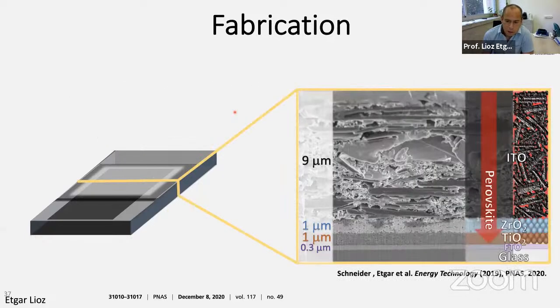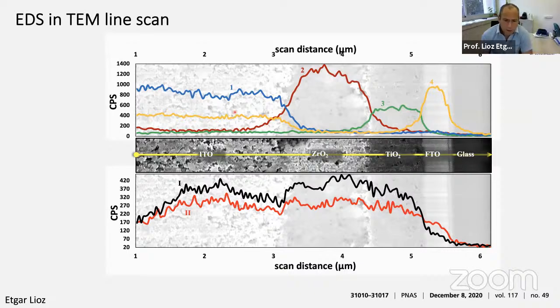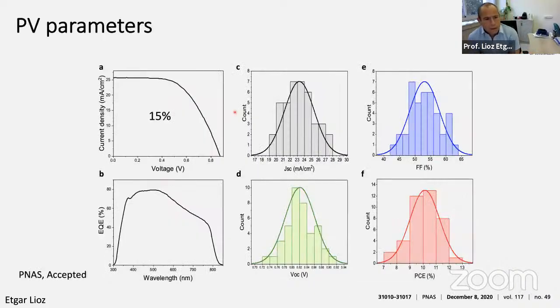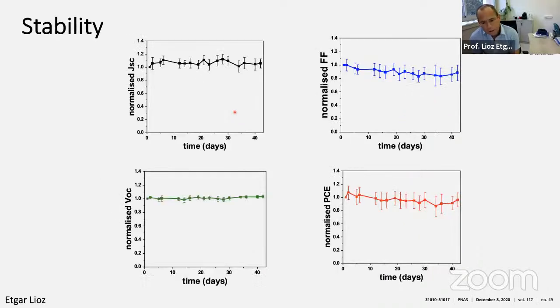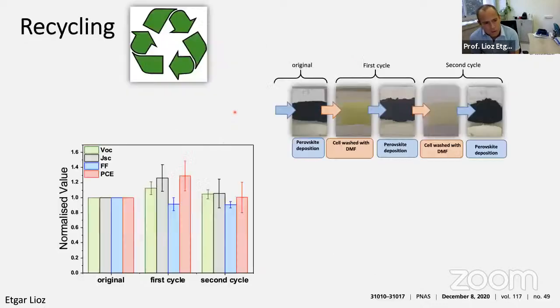Here is the cross-section of the different layers. And here again, we also did some EDS line scan. So this device gives today an average of 15% efficiency, quite impressive for those newly developed devices. Stability is amazing since we are not dropping at all the performance for all the parameters.